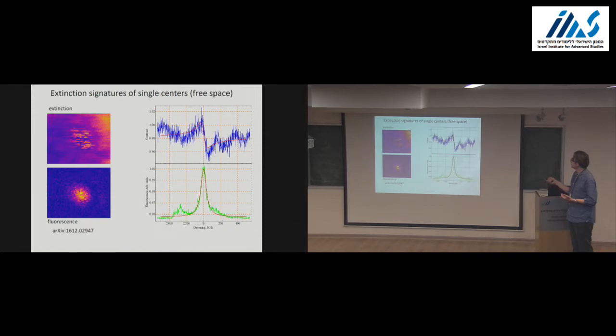At the same frequency you now get this dispersive profile. That happens because the photon reflected from the surface of the diamond interferes with a coherently scattered photon from the atom. And so this contrast here, which can be a few percent, up to 10% in free space, is now related to the coherent part of the interaction of the atom and the light.